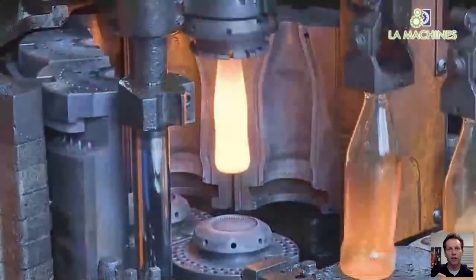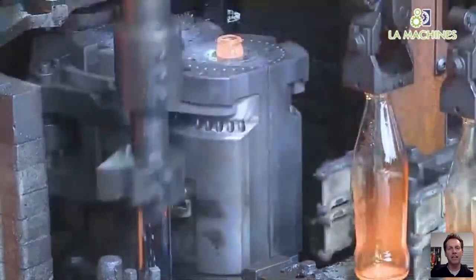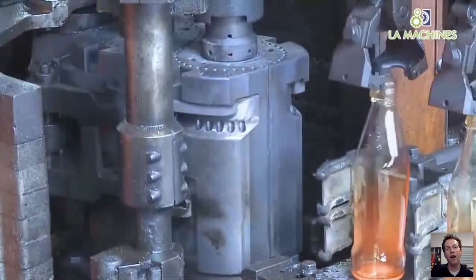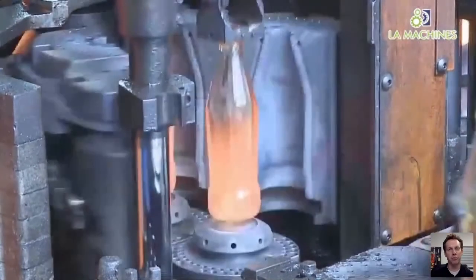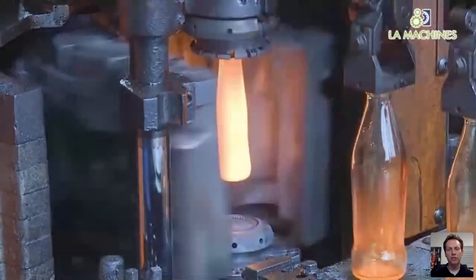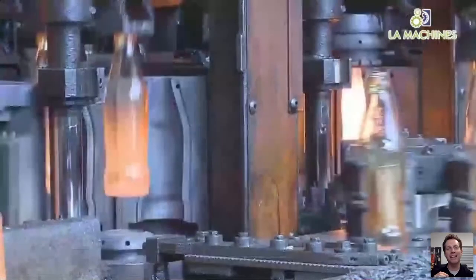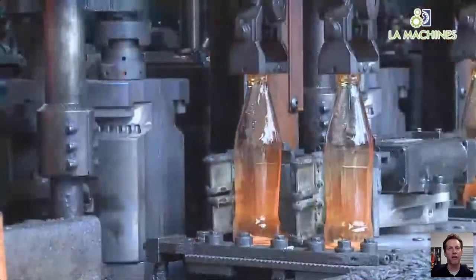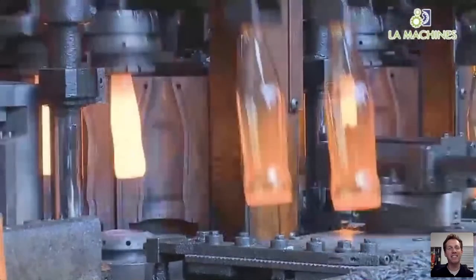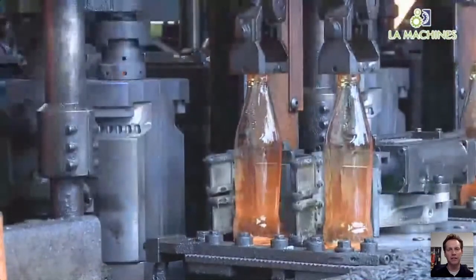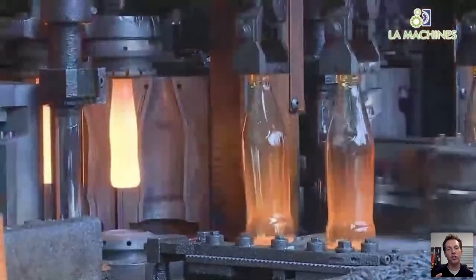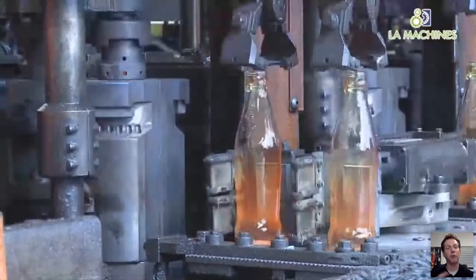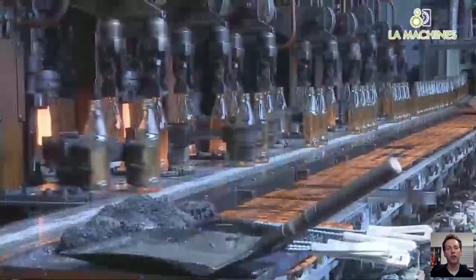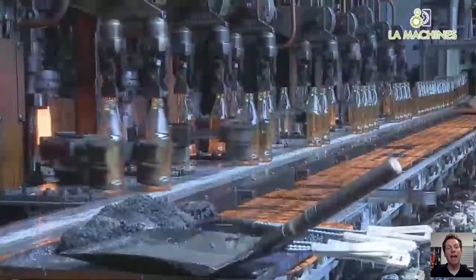One of the big drivers for the cost of these bottles is how fast they can get these glass bottles to cool down enough so that they can be self-supporting and go get annealed. And you can see these molds are gray. They're gray cast iron, and they're gray cast iron because it handles the abrasive molten glass very, very well. The problem is it doesn't get rid of heat super easily. So the desire is to switch this material from cast iron to bronze, since bronze will get the heat out far quicker and allow you to run that line faster and bring down the cost of each bottle.